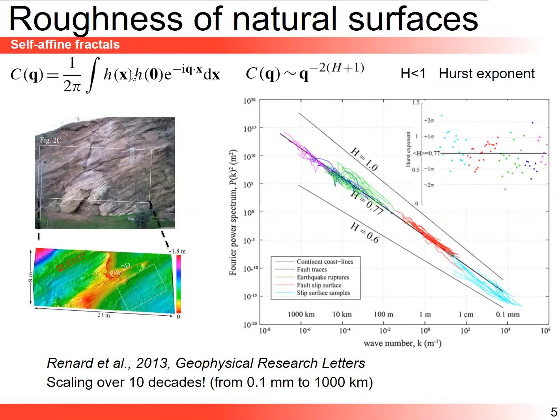H is the height at a material point X along a surface. And if you take the Fourier transform, if the surface is self-affine, you find that this Fourier transform is a power law of the wave vector Q with a well-defined exponent. This exponent is related to what is known as the Hurst exponent. H is called the Hurst exponent.